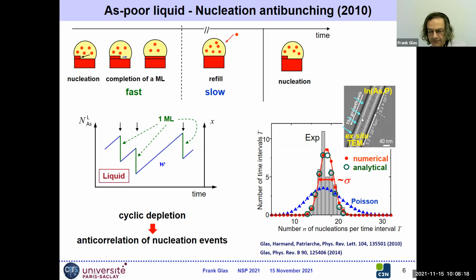Now, if we assume that the nucleation events that give rise to each monolayer are independent of each other, then you all know that what we expect is a Poissonian distribution. The Poissonian distribution equivalent is the blue curve here, and it's quite obvious that the experimental histogram is much narrower than the Poisson distribution. So this told us immediately that the nucleation events giving rise to each monolayer were not independent, and in fact that they were anti-correlated.